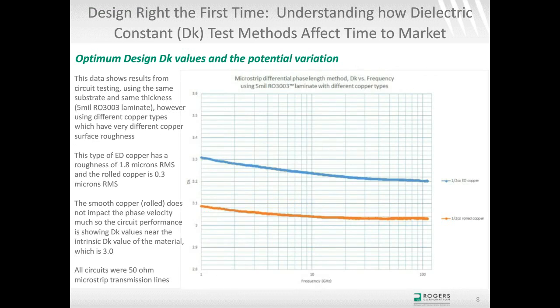Another way to look at this, again using the RO3003 laminate, is in this case thin, 5 mils thick, but I used two different coppers: one is a rolled copper, the orange curve, and the other one, blue, is the ED copper. The blue curve has a surface roughness average of about 2.0 microns RMS, even though my notes say 1.8. More recent data says it's a little bit rougher than that. And the orange curve, rolled copper, has surface roughness of about 0.35, again, we have 0.3 in the notes here, but the more recent data says it's just a hair rougher than that.